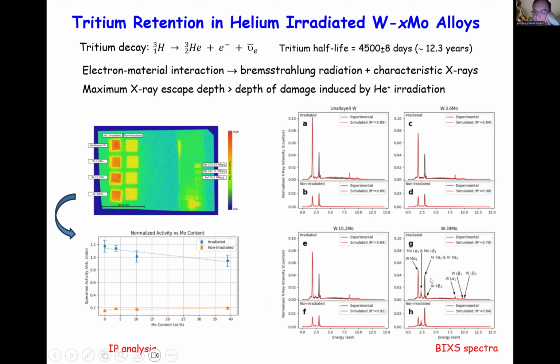You see a number of peaks. Those are from tungsten and molybdenum. You also see argon, and that's because we did the experiment, or the spectroscopy, in an argon environment. So the X-rays that escape from the material before reaching the detector also go through some argon, but it's not from the material itself.